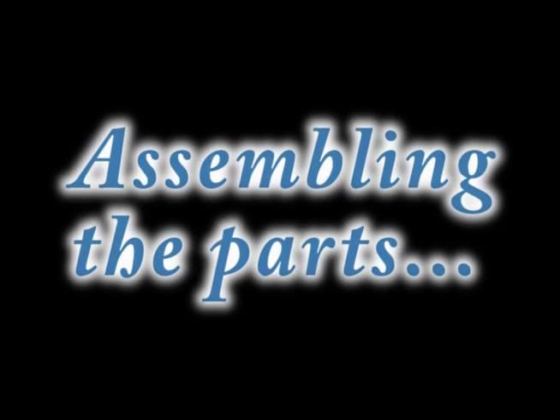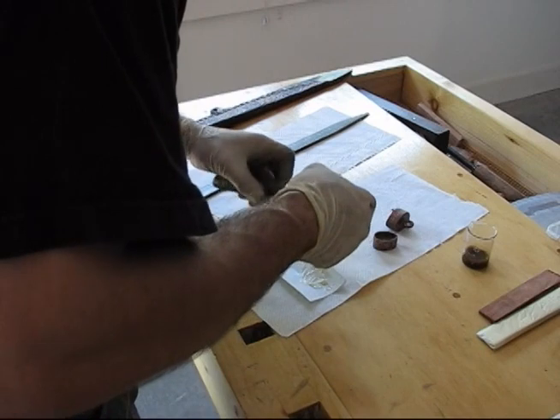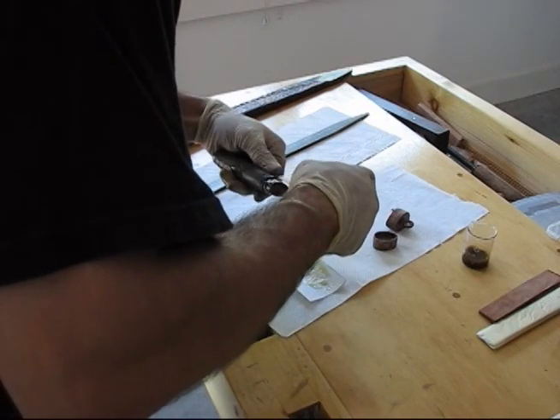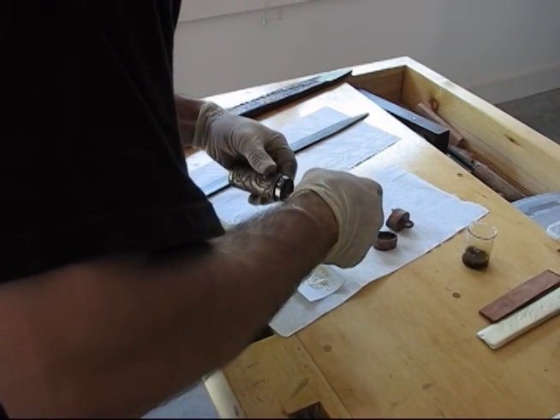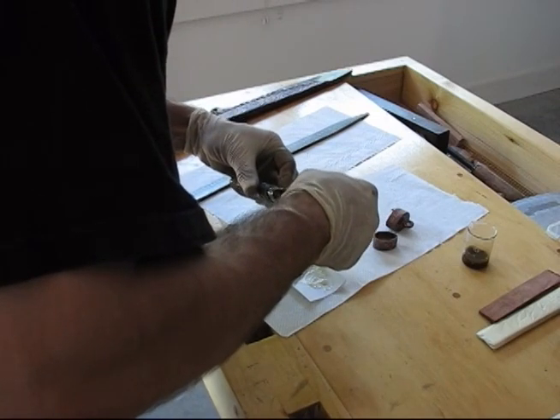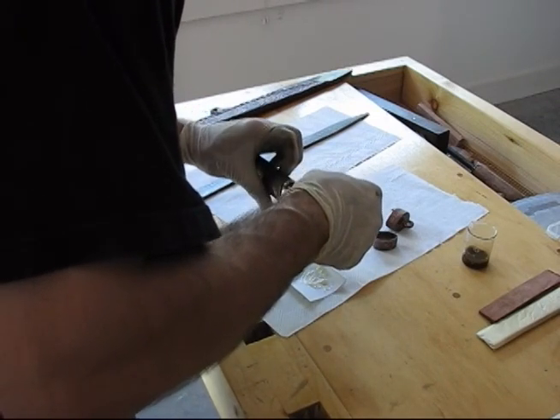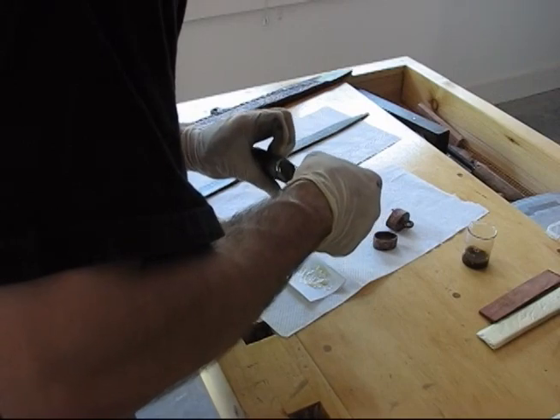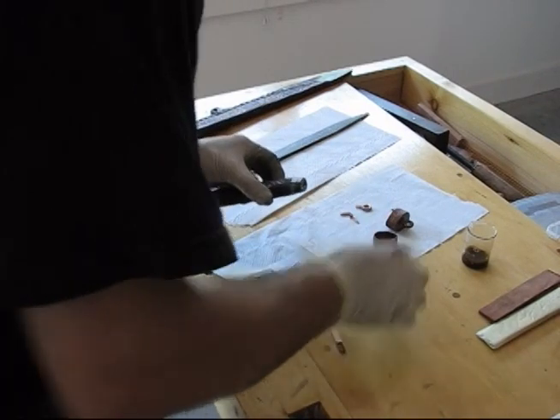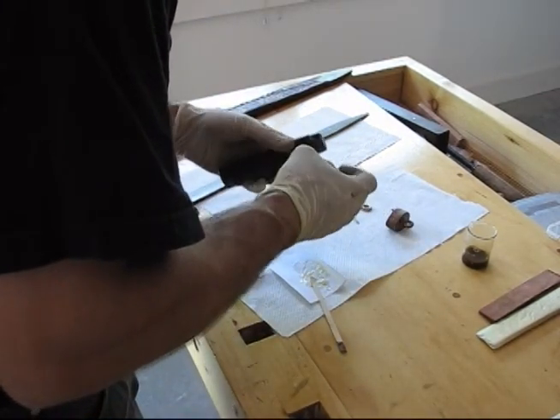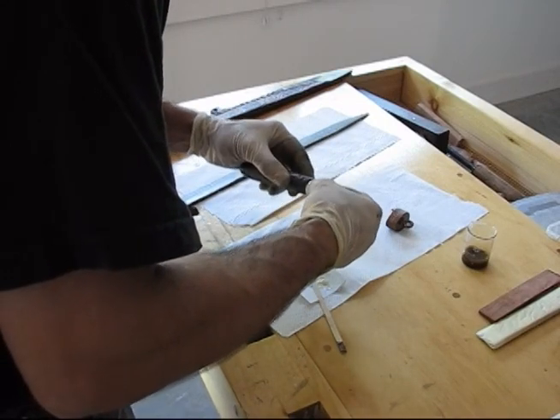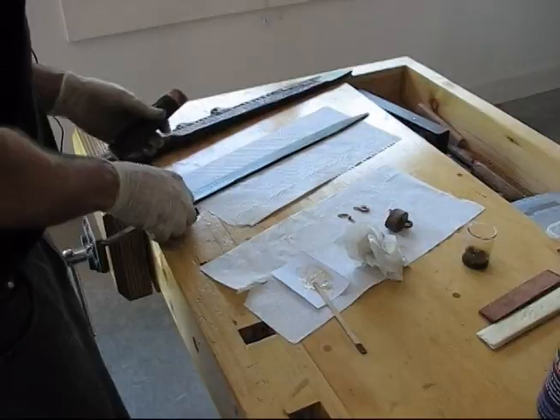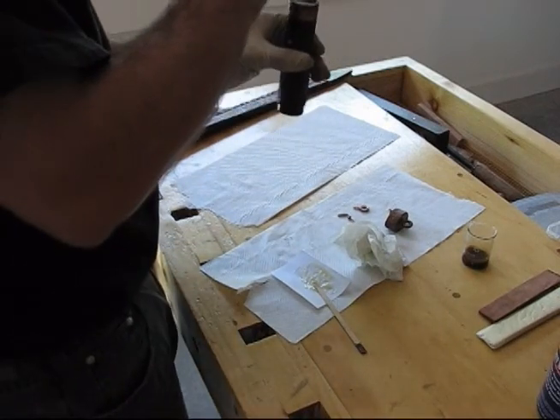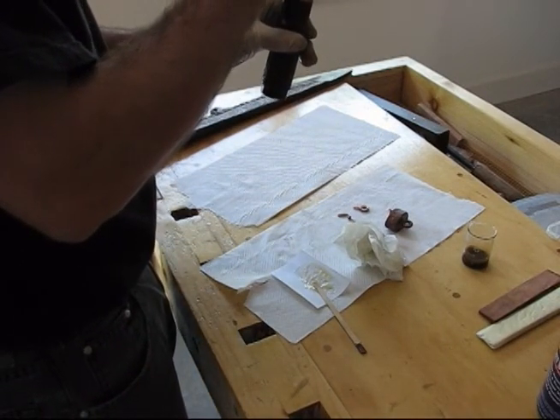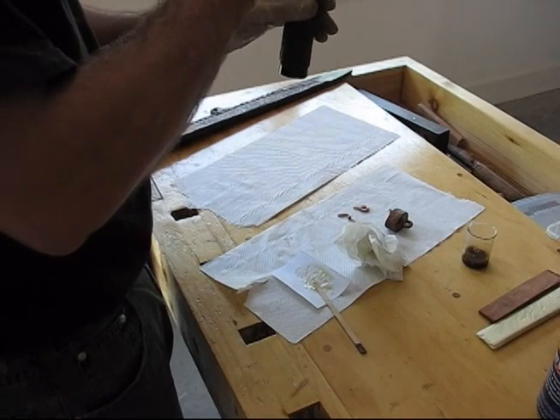All the different parts can now be put together. Traditionally, it is likely that the handles were glued using pitch. Jesus uses a 2-part epoxy, as the setting time for the pitch is too short to assemble this many parts. First, the ferrule is attached. Then the blade is set in the handle and locked into place using the cross pin.